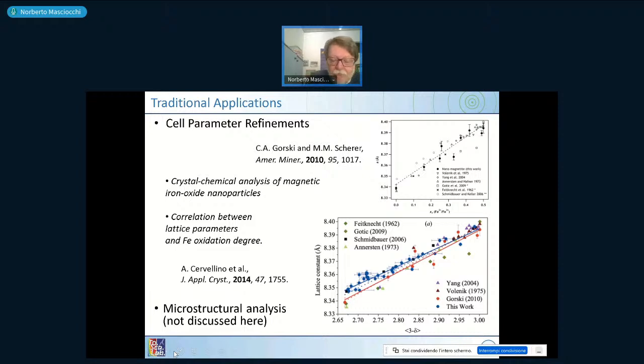One of the outcomes of the analysis you can do is measure the peak position accurately, and the peak position gives information about the distances in the material, and the distances normally depend on the material nature. For example, if you take magnetic nanoparticles, iron oxide, you can have iron 2 and iron 3 in a different ratio, and the ratio between the two is highly dependent on the aerial exposure, on the temperature, on the storage